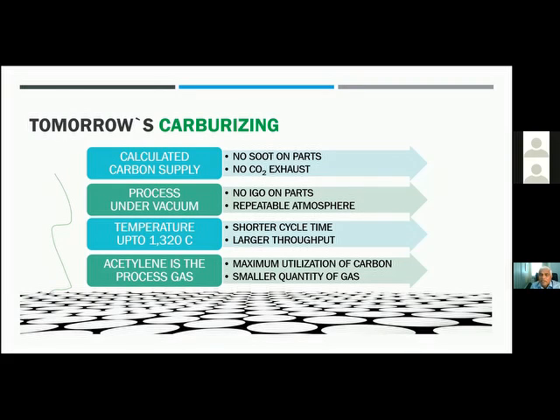The second advantage of doing it in vacuum is that the laws of physics hold good. Every time I achieve a 7 torr or 8 torr or a 10 torr vacuum, Boyle's law will hold good because PV by T is constant. So every time I get a 10 torr pressure, I can be assured of a certain lower concentration of oxygen. And this process can be repeated again and again, which means I can have a reliable and repeatable atmosphere, which I can never ensure with a flow of methanol, nitrogen, or endogas. This is a huge advantage when standardization gets into a big kick, in organizations which are very large, which depend on documentation to prove every cycle and batch that you've done.